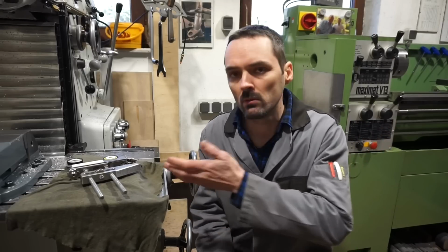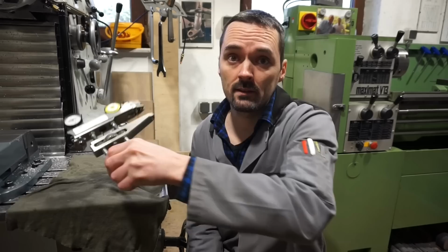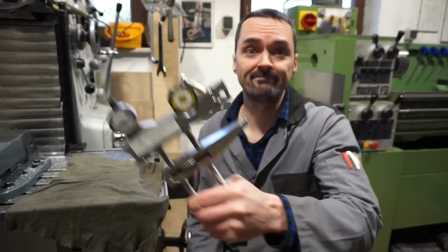And lastly, there is another application for hardness testing: to very roughly grade materials. Let's say you have a mixed up material bin where you have quench and heat treated tool steel and some mild steel, and it unfortunately got mixed up. So with hardness testing you can very quickly sort this out. You cannot sort out between alloys of the same strength, but at least you can roughly sort it out. If you only have two alloys in stock, for example, then this is a very handy method. So enough talk now, and let's see what this tool can do.